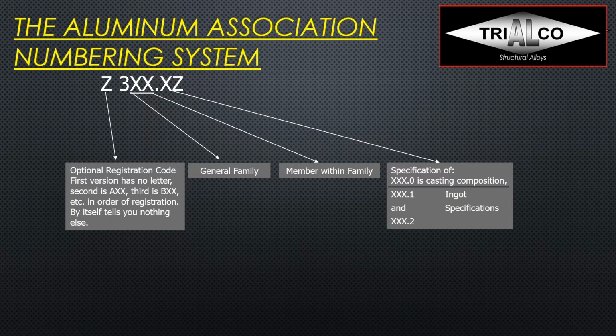So very important here, the dot 0 is the casting composition. So that's what we want to achieve in the casting after it's cast. So you got to subtract whatever you burn off in the process, and you have to add whatever you pick up in the process, like iron, for example. A dot 1 is an ingot specification. So usually you will see slightly higher purity in terms of iron and things like that you will pick up. And usually you will see a little bit higher strontium or magnesium or anything that you burn off. And some foundries will obviously burn off a little more or pick up a little more than others. And therefore we have also a .2, and .2 is then the higher purity specification.